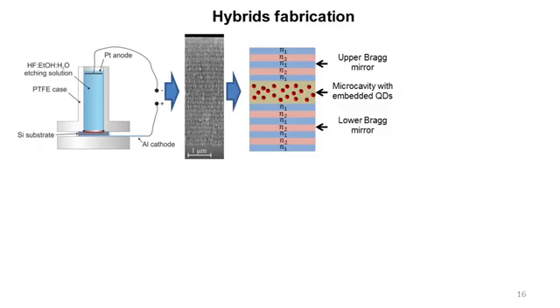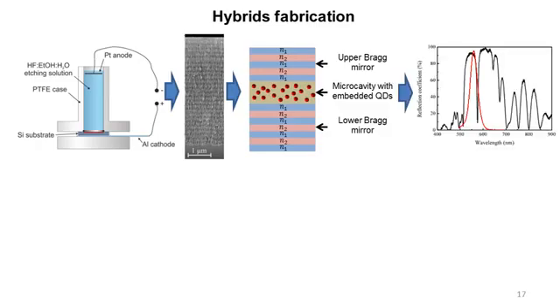dots. The photonic band gap of the microcavity was about 150 nanometers wide, with its resonant mode concentrated at 580 nanometers, and its quality factor was about 83. This microcavity design was chosen in order to provide partial matching between the quantum dots emission maximum and the microcavity resonant mode, and to suppress the rest of the inhomogeneously broadened photoluminescence, which remained uncoupled.